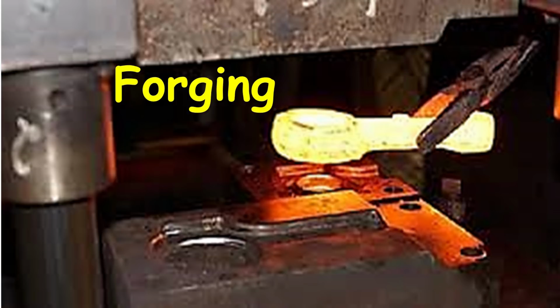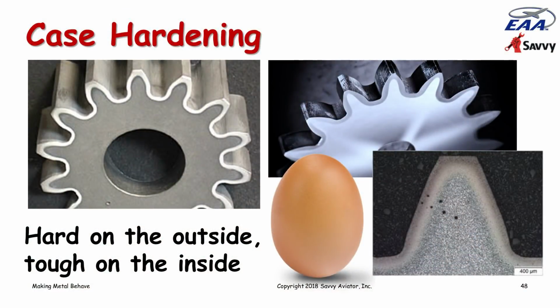Now, sometimes we don't want to make the whole part harder. We just want to make the surface harder. Here's a perfect example, gears, where we'd like the surface of the gear to be as hard as we possibly can, so it has really good wear characteristics. But if we made the whole gear that hard, it would be vulnerable to fatigue fracturing, because the harder the metal is, the more brittle it is. And so we really want the inside of the gear to be tough and the outside, the wear surface of the gear, the very outer layer, to be very hard. The same thing is true of lots of other components like camshafts and crankshaft journals. And the process of hardening just the surface of the part is called case hardening.